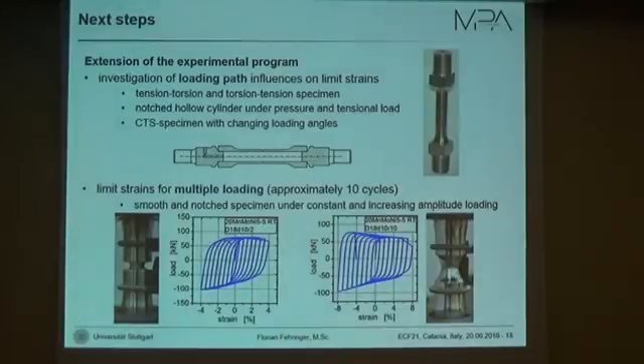For the loading path influences, in addition to the pre-strained notched bars, we have tension-torsion and torsion-tension specimens, which we will load also in 2 steps, not simultaneously. And we have notched hollow cylinders under pressure and tensional load, where we will apply pressure and afterwards the tensional load to see the influence of the changing stress triaxiality. And the CTS specimens, the compact tension shear specimens I showed in the slide before, we will also use in 2-step tests, changing the loading angle at least once during the experiment.